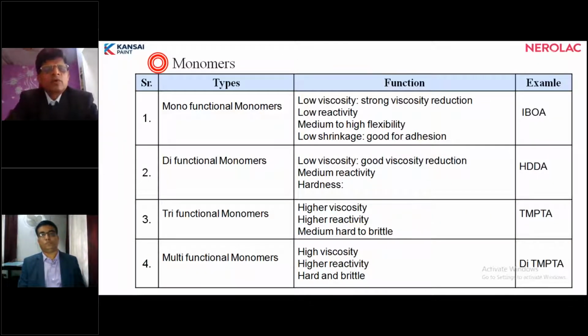The second most important part is monomers. Monomers are reactive diluents, so we can use them to reduce the viscosity of UV curable coatings. If you take monofunctional monomers, they reduce viscosity and are low reactive, for example IBOA, that is isobornyl acrylate. The second one is difunctional monomer, which has low viscosity and is medium reactive.